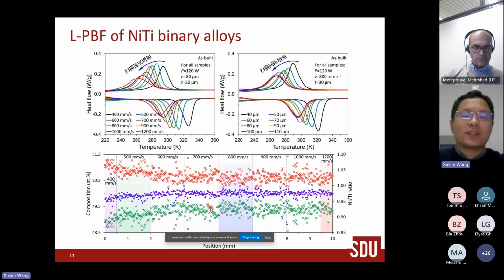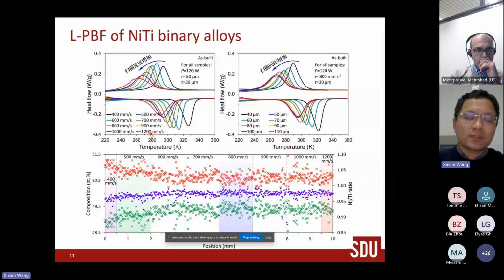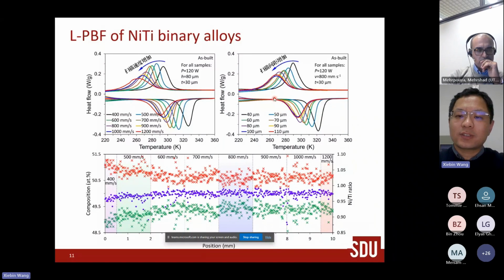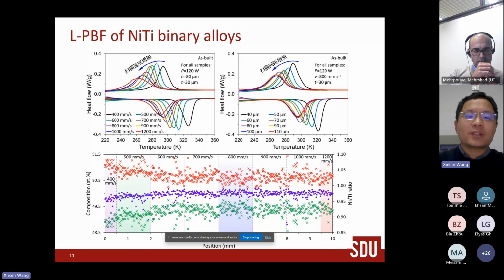And then we checked the phase transformation behavior. It's quite interesting that the transformation peaks shift gradually to the lower temperature side if you increase the scanning speed. Of course, you keep the laser power, hatch spacing, and the layer thickness constant, and only change the scanning speed. So the transformation temperature decreases with the increase of scanning speed. And of course, it also decreases with the increase of the hatch spacing. So it means that if you decrease the energy input, the transformation temperature decreases.